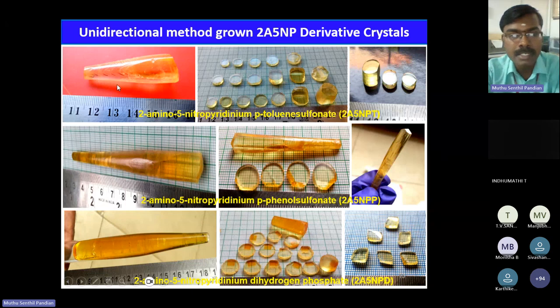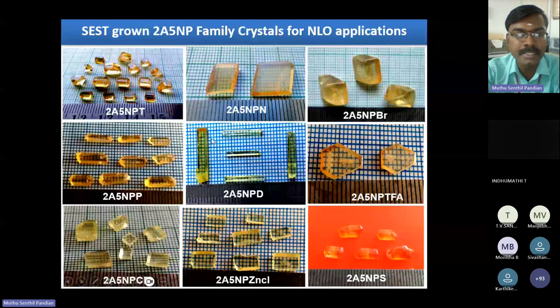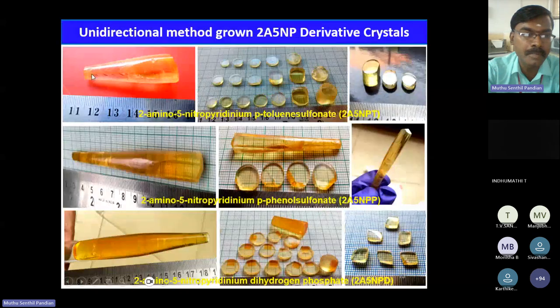So this is the crystal grown by the conventional method. The same crystal we use as a seed crystal. We mount it at the bottom of the glass ampoule and we grow this much larger size single crystal by this SR method. So these are the as-grown crystals by this SR method, and these are the cut and polished